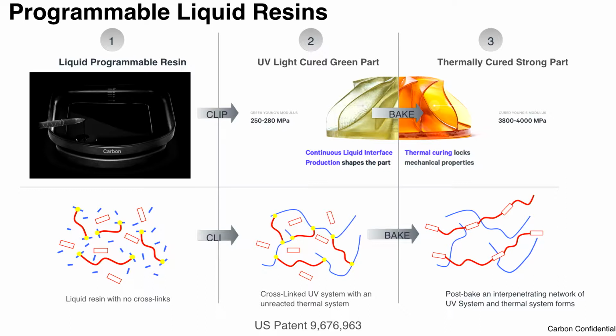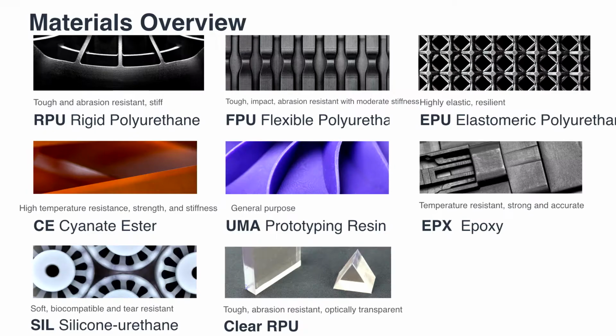In the green state it comes off, it's about 250 to 280 megapascal modulus. After the bake, it gets up to about 3 to 4 gigapascal. So it's a very, very different material. And this has allowed us to get into a wide range of material properties, ranging from our rigid polyurethanes, which are more akin to PC/ABS, ABS. They have about 120% elongation at break, very, very tough material, to our flexible polyurethane materials that's more akin to polypropylene, over 200% elongation at break.